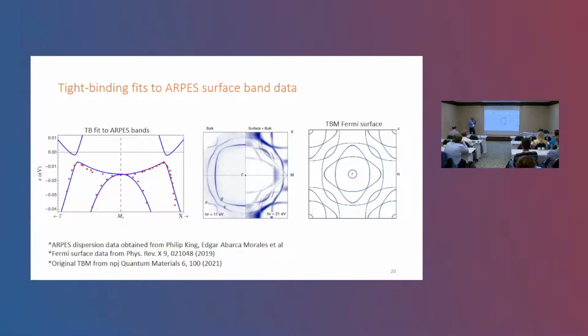But this is the conclusion so far, because it turns out that experimentally it's not clear at what angle precisely the octahedra are rotated. So we are fine-tuning from the experimental results to see if it's possible to merge these two saddles to a higher order Van Hove singularity, or this is the final answer to the question.